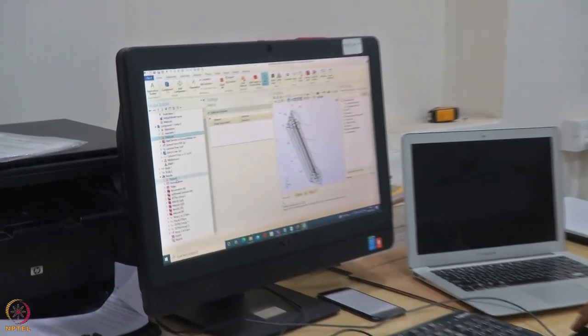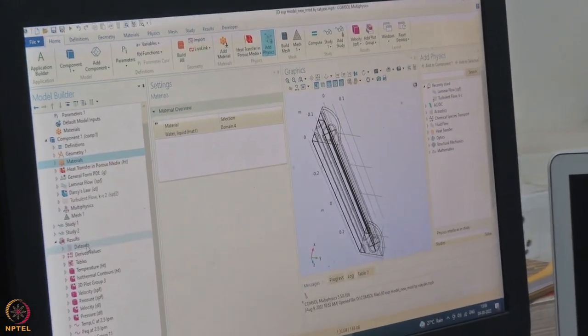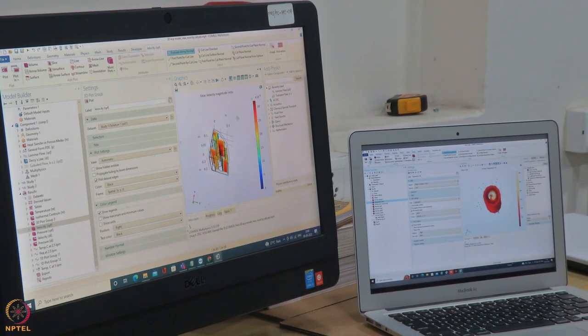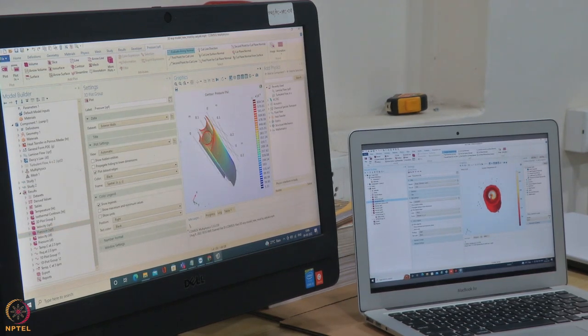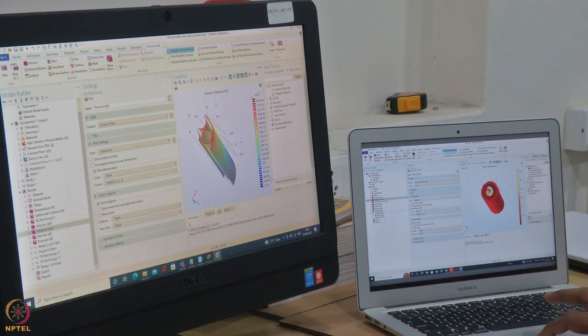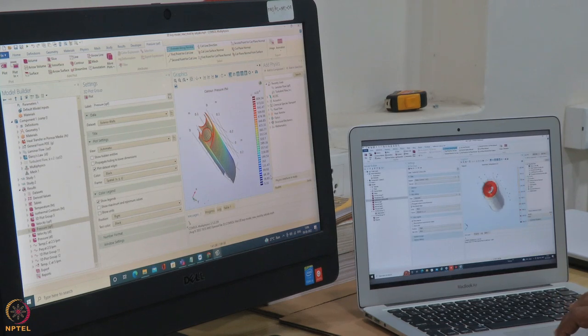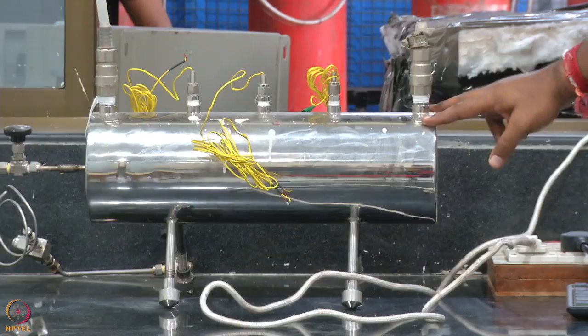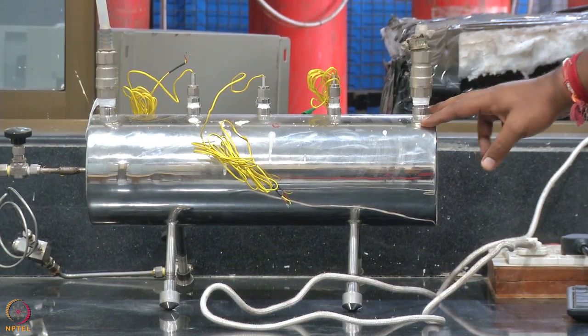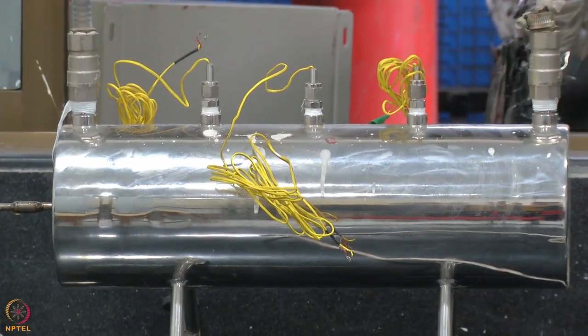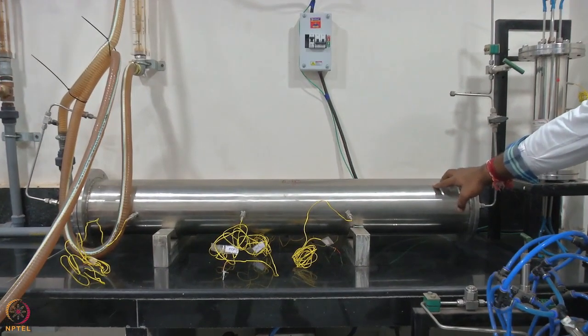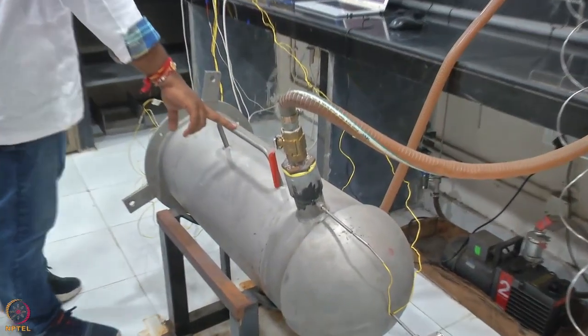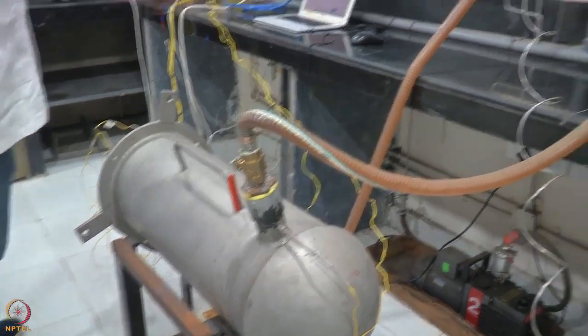After synthesis via ball milling, arc melting, or induction melting, metal hydride reactors are fabricated. Before fabrication, the reactor behavior is investigated using simulation software such as COMSOL, ANSYS, and MATLAB, studying the effects of various parameters on absorption and desorption, and applying machine learning-based optimization. This saves time, resources, and cost. The optimized system is then fabricated at scales from 1 kg to 50 kg of metal hydride, incorporating various heat transfer arrangements such as embedded cooling tubes, hexagonal fin type reactors, and modular type reactors for applications like heat pump, heat transformer, and thermal energy storage.